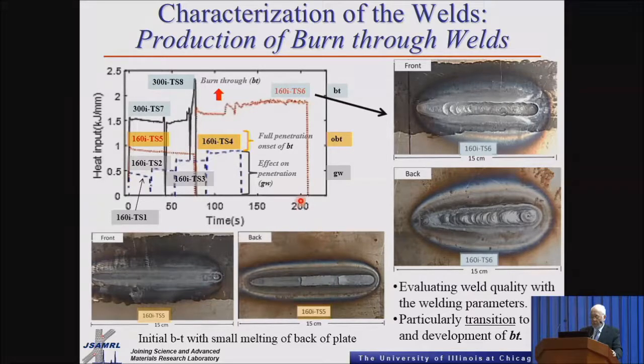Now, if we go to this particular one, we have in here the high heat input. So you go to 300, TS7, and in this particular high heat input, you can see some depression in the weld bead, and this is the front of the weld. On the back of the weld, you can see some of the metal coming out, and we define that as a burn through. So in between these two heat inputs, the lowest heat input and this one in here, indeed, we have some type of the onset of burn through.